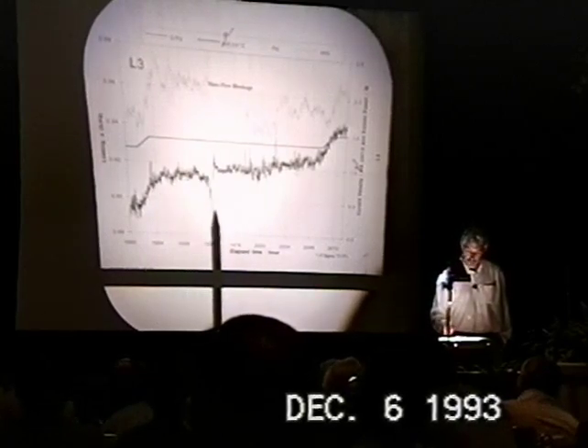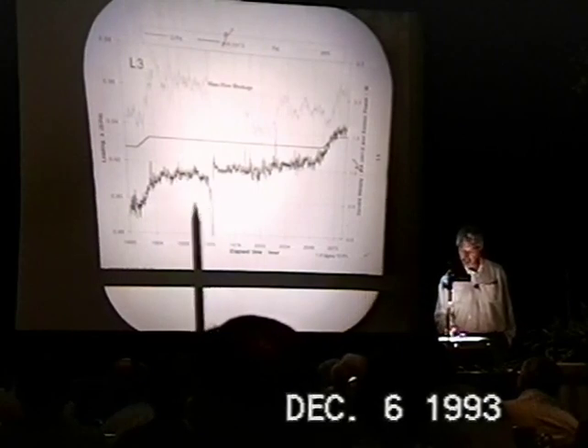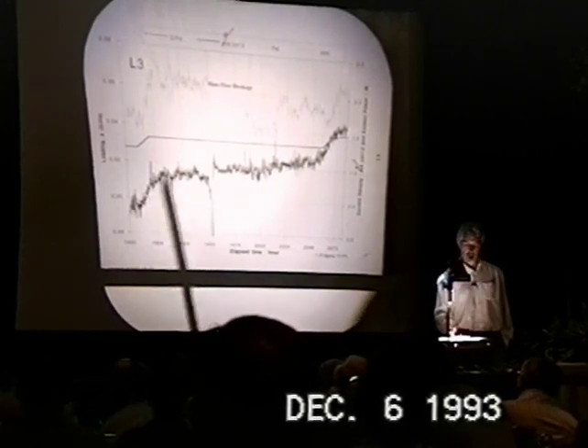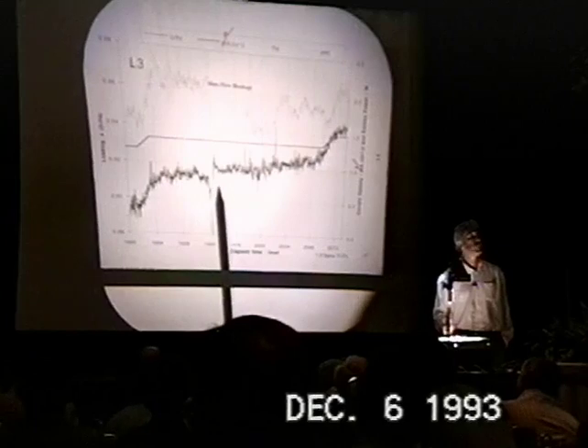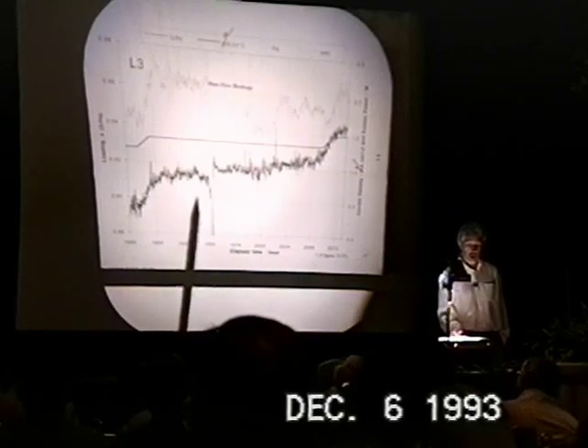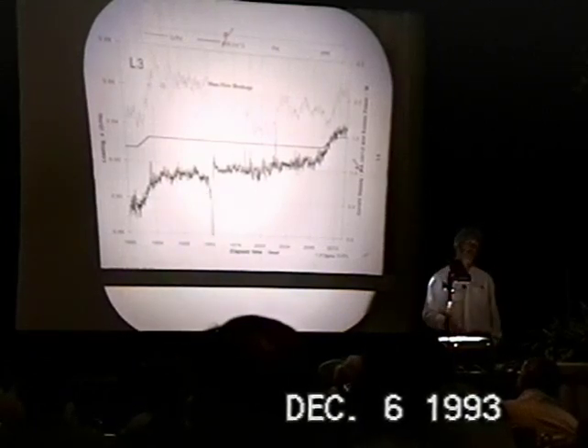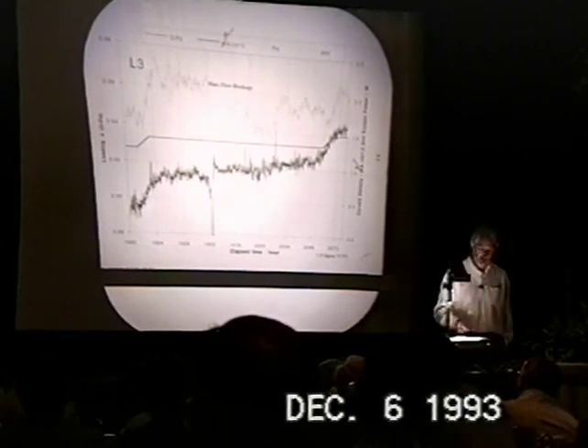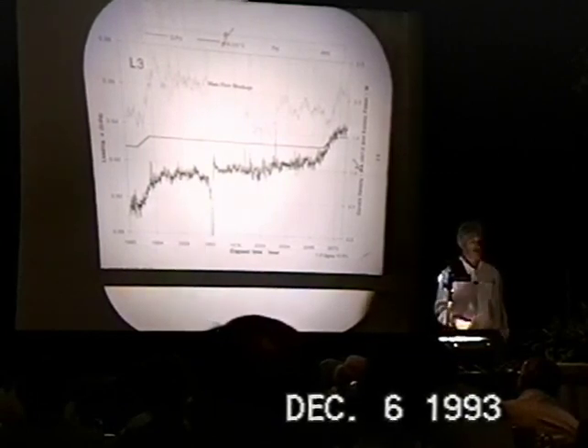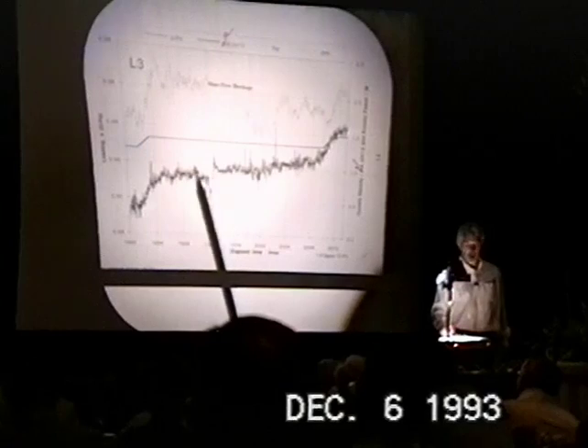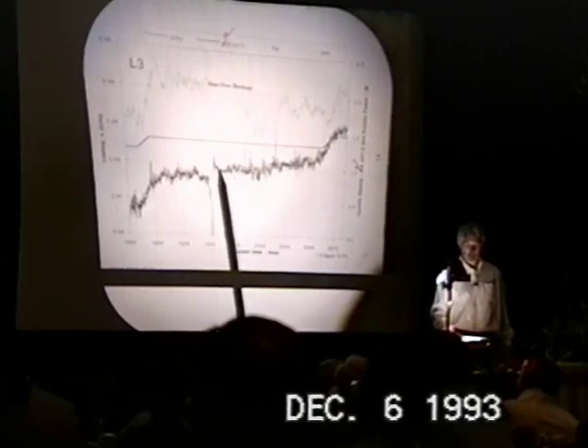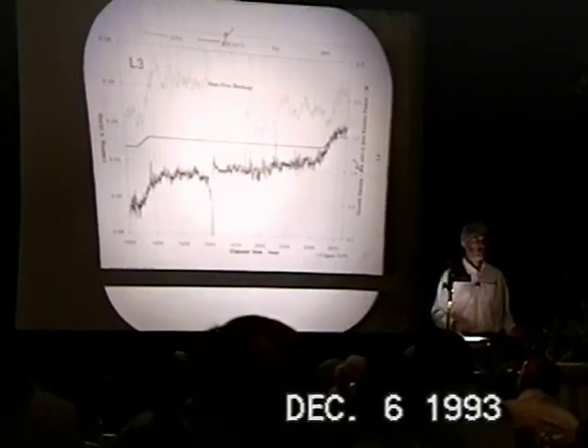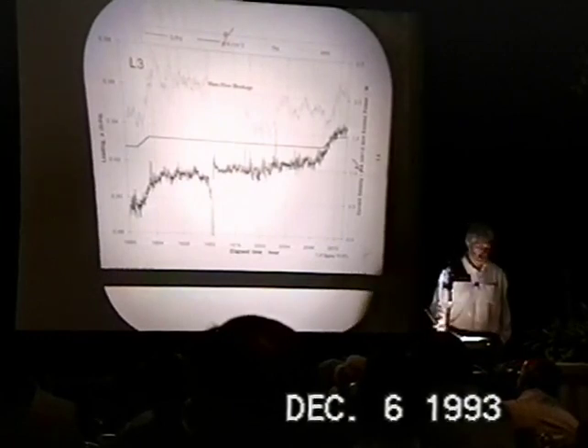It could be that the loading tried to come down a little bit from 0.92 down in the direction of 0.9, but it also might be that I'm simply underestimating the resistance of the cathode, which would also cause the apparent loading to decrease. But in any case, after the event's all over, within a day, the loading of the cathode is the same as it was before. It is going up.